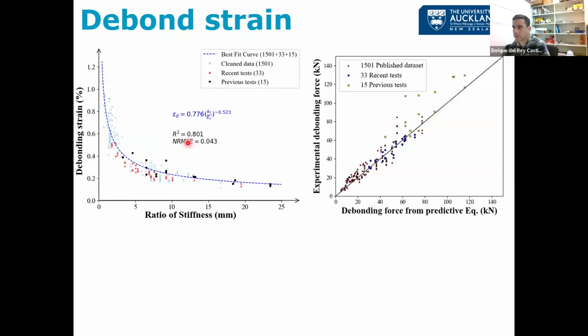So we did a whole bunch of tests, like I said before, I think 1,600 or 1,800 in total, collected from the literature and some that we did. And we realized that it's not about the strength of the concrete and it's not about the strength of the FRP. It's the ratio of the two that is determining the strain at which the FRP starts debonding.